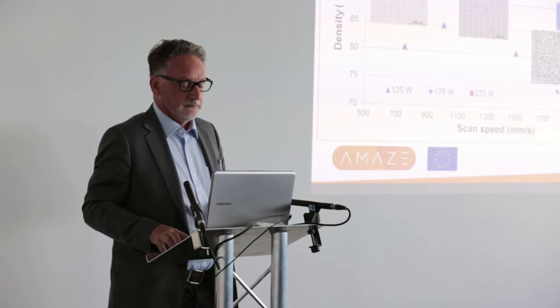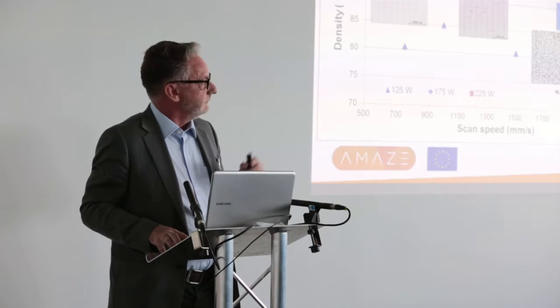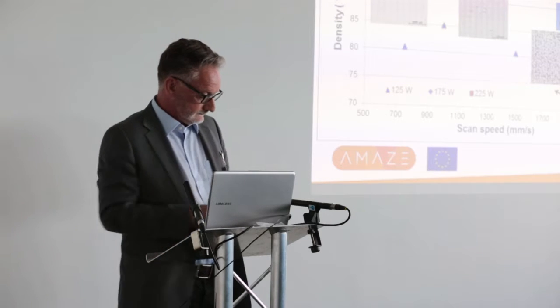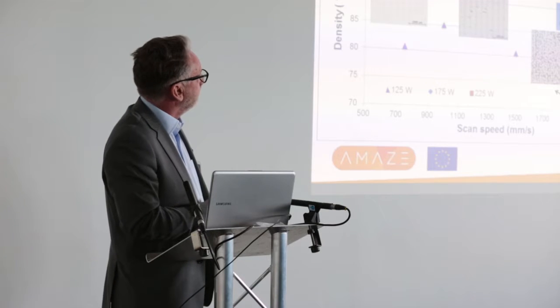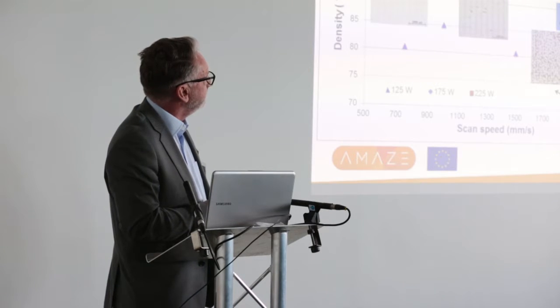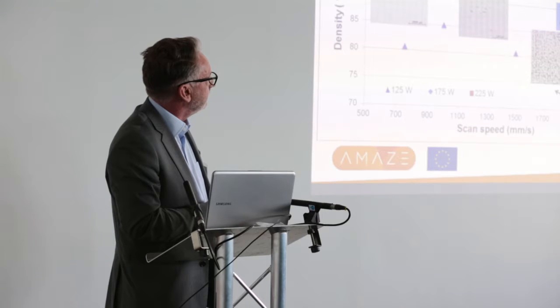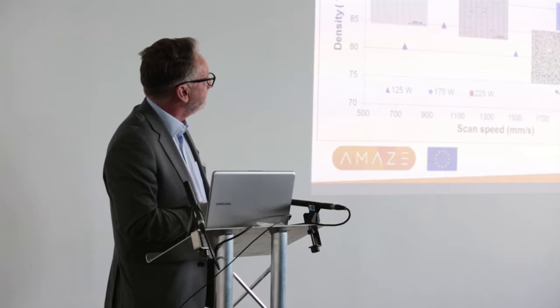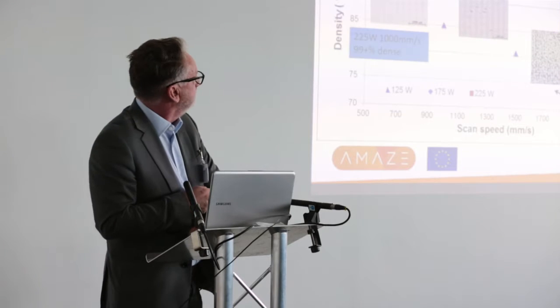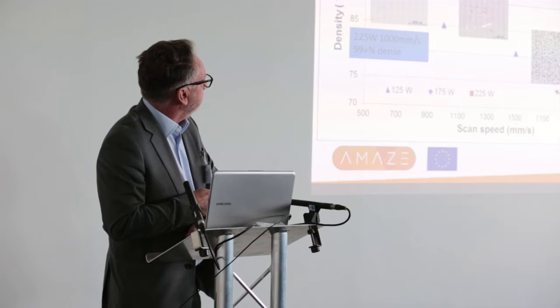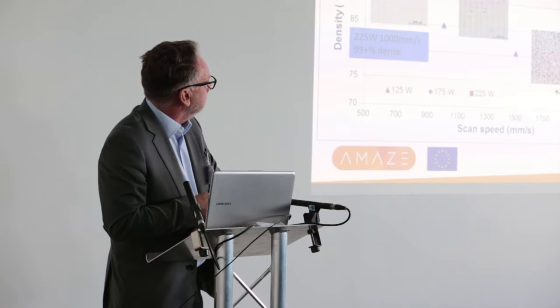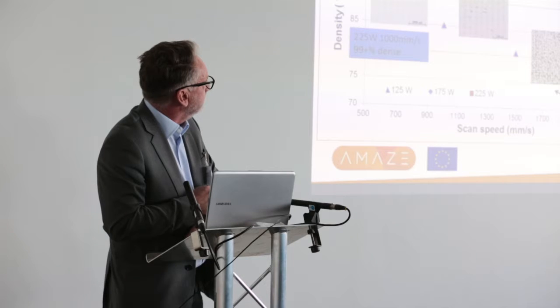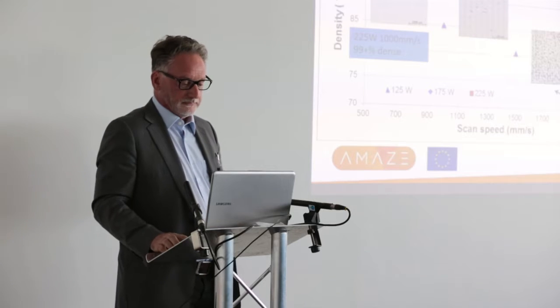So this is just one of the examples of the sort of properties we can measure. So you can see at lower power, you are not getting full density. It's only 125 watts at quite a high speed, and the density of that is only about 70%. But as the power is increased, then you can get towards full density. So as the power was increased, this is 225 watts power, and the speed was slower, then we were able to get to full dense parts.